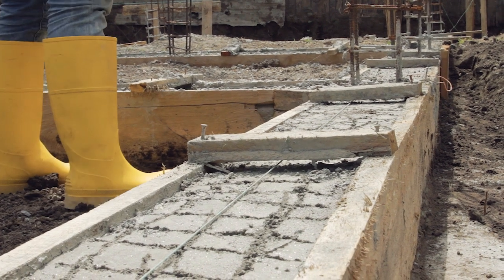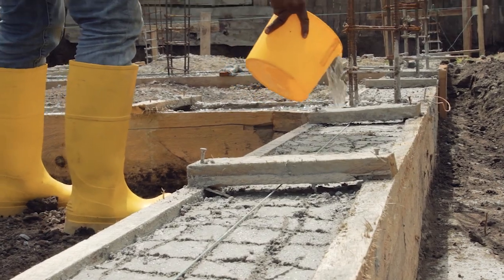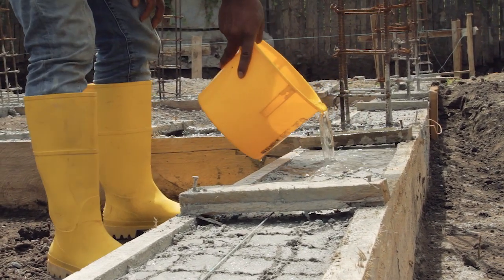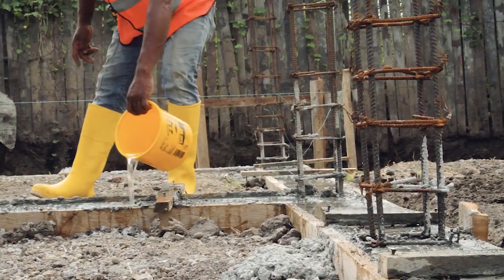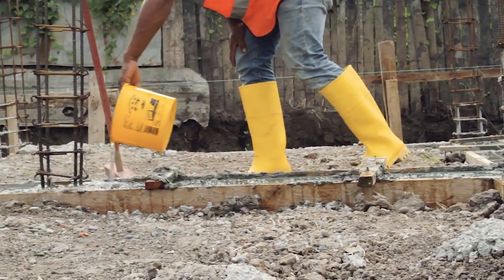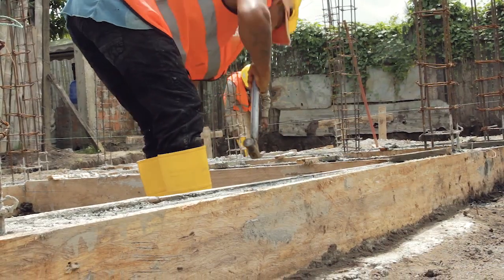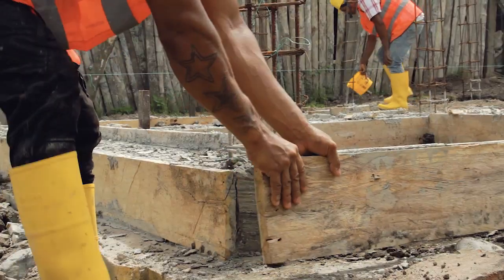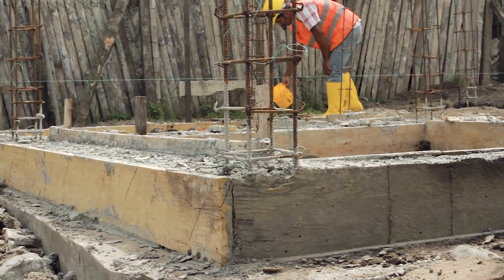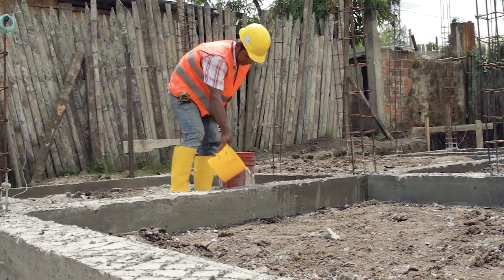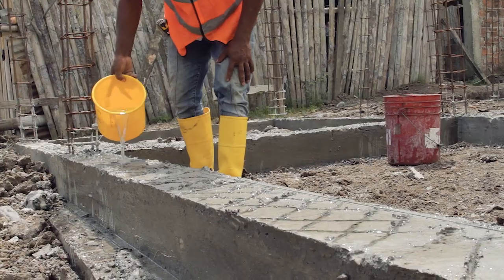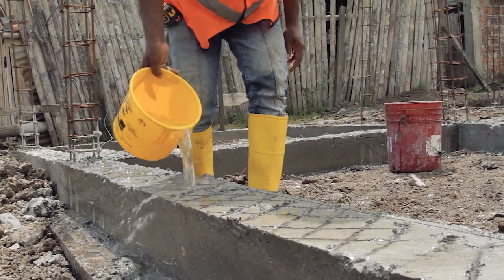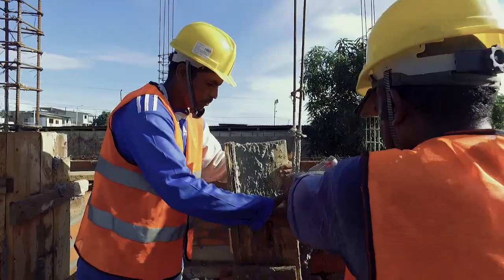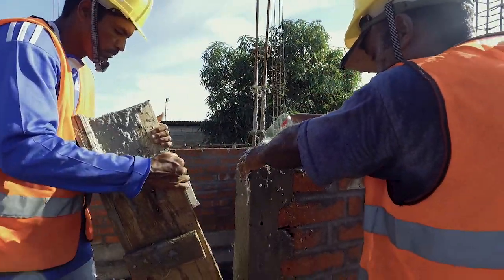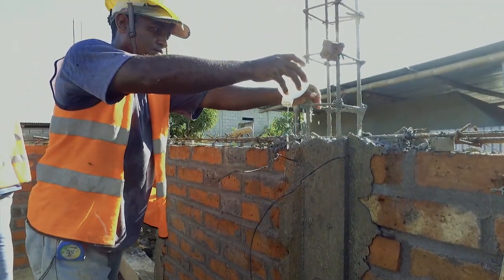Curing the concrete. If concrete is left to dry, it loses its water by evaporation and becomes less resistant. To avoid this, the formwork must be kept humid for 3 days, and only after can it be removed. Once the formwork has been removed, the concrete must be kept humid for 7 more days by wetting it and covering it with a plastic sheet to avoid evaporation. This process is called curing and must also be done for the tie columns.